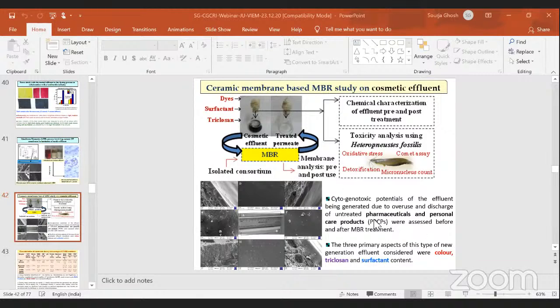That is, wastewater was collected from a spa and analyzed. Three major contaminants were located: one is the dye, another is surfactant, and another is triclosan. So we observed the removal efficiency using our MBR process, membrane bioreactor process. This is the ultrafiltration membrane used for the study. And we found that the treated water was free from color, triclosan, as well as surfactant content.